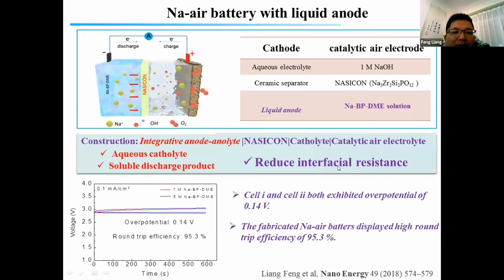Also, in order to improve the safety of this battery, we replace the sodium with a liquid. So by using the BP and DME solution to replace the sodium, in this case, by using this liquid anode, the interface resistance between NASICON and anode can be reduced. Also, this battery demonstrates a very high energy efficiency, about 95.3%. So the overpotential is very small. So it's a very good result.